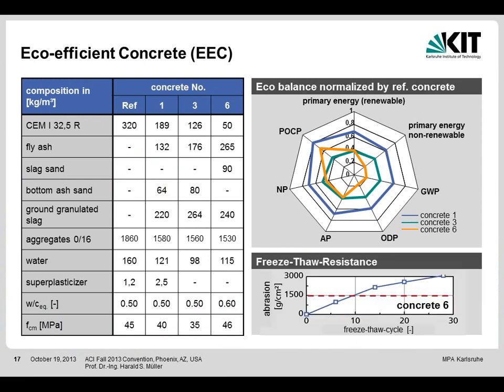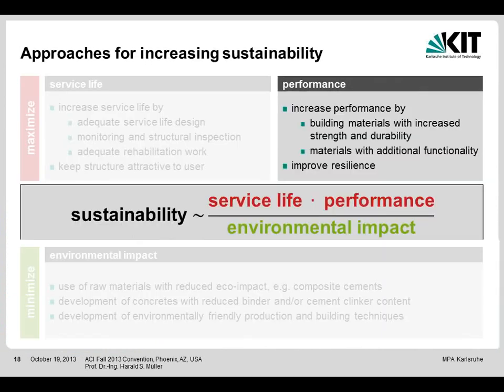But, as already has been mentioned, there is a problem insofar as to gain the strength is no problem, but to gain durability, that's the problem. The frost resistance of this concrete is very bad. After 10 cycles, it crosses the limits, and insofar it is not suitable in cases where we have a frost attack on the concrete. My last approach is to look to the performance.